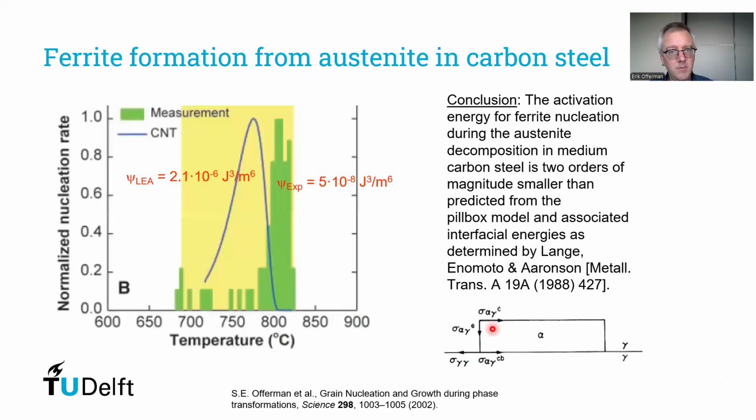Okay, then we did, during the time that I did my PhD, a synchrotron radiation experiment. The third generation synchrotrons had just become active and had this newly developed technique of 3D XRD microscopy, by which you can measure in situ the nucleation rate.